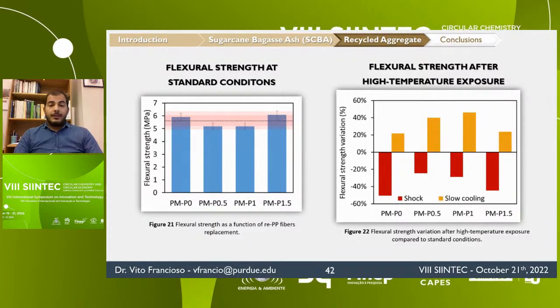On the other hand, the slow cooling increased the flexural strength compared to the samples tested under standard condition. And this enhancement is specifically higher in samples with polypropylene fibers. Since the matrix is the same, these results suggest that the bonding between the fibers and the matrix was enhanced after the high temperature exposure of slow cooling.